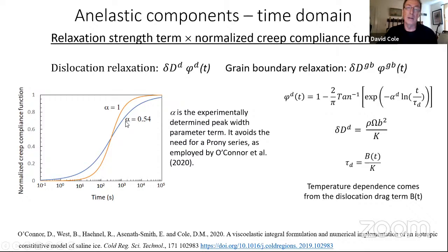When you have a polycrystalline material, each with its own relaxation scale, variations in grain size and length of basal planes, etc., you actually have a distribution in relaxation times because you now have a coupled system of relaxing elements. There's a clever way that I found, actually in a footnote in the Nowick and Berry Anelasticity in Crystalline Solids book from 1972. It's the only textbook where I found this relationship. The beauty of that is it gives you a one parameter term to account for a distribution of relaxation times. Jumping track, and the paper covers these other topics in more detail.